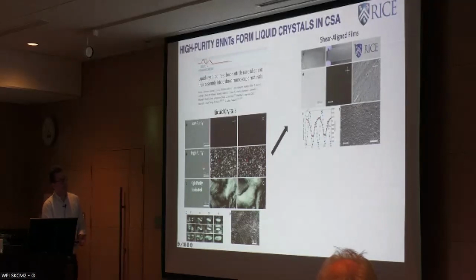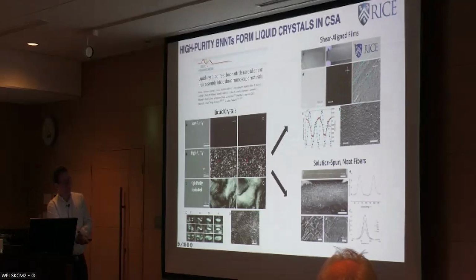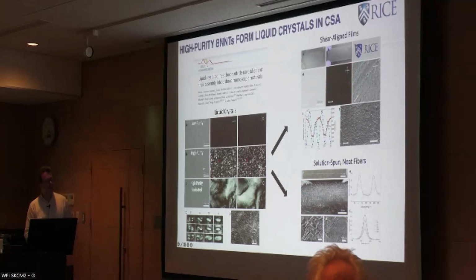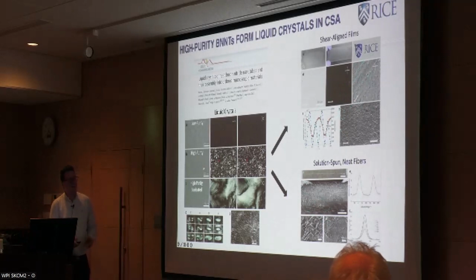and then you can make films that, for example, are shear aligned. Here you see as you rotate the polarizer and the analyzer, you see how the film has alignment, and you can also make fibers. Now, this is about as good as the carbon nanotubes were in 2004. So that's why there's no samples, because these are much more fragile and not something to take to a distinguished conference to brag about. Okay, but it's encouraging.